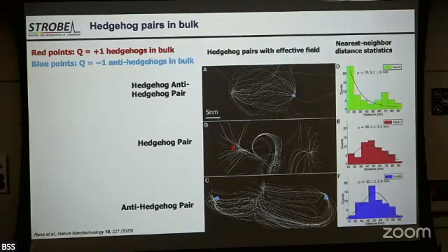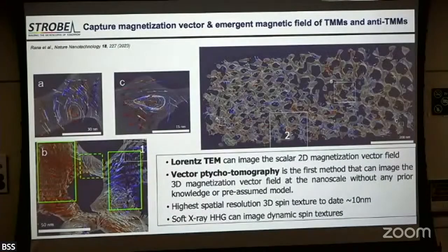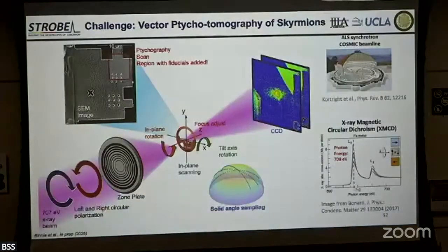nickel nanoparticle spacing. So the interesting thing about this, at the time, is it makes no prior assumptions about the sample, which needed to be made using other techniques. So it's a general method. Then more recently, we did an even harder experiment.